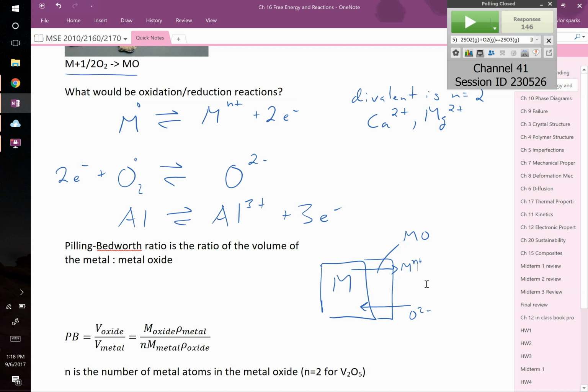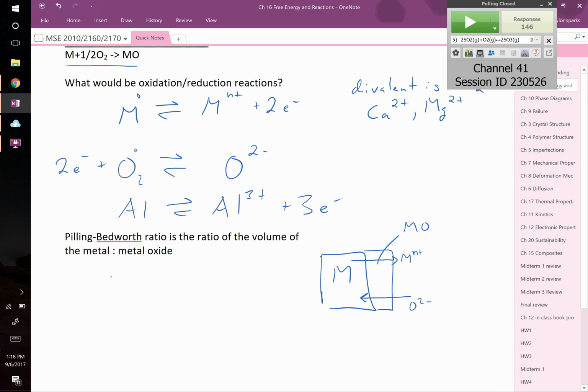When you grow this oxide, the way that I drew this, the metal oxide layer basically matches the metal underneath. But what if when you grow it, let me move this down, give myself a little more space, imagine you've got a metal, and when the metal oxide grew on your metal, it's bigger. It just takes up more space. Then when that grows, it's going to be strained. And we know that ceramics, because metal oxides are typically ceramics, don't tolerate strain, something we'll learn a lot more about in a few chapters. It can't just be squeezed very easily. Instead, it's going to spall off. Spall off is when a scale comes off, and you've seen this.